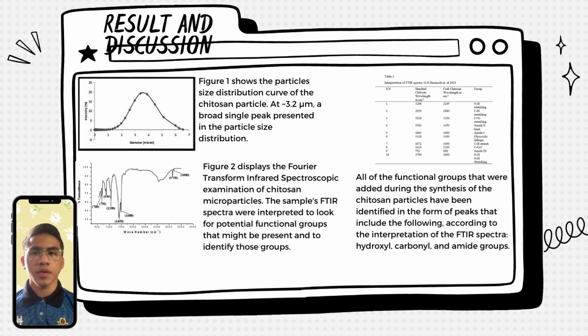The second one, figure 2 displays the FTIR examination of Chitosan microparticles. The FTIR spectra were interpreted to look for and identify all potential main functional groups that might be present in the Chitosan microparticles. In table 2, all the functional groups present during the synthesis of the Chitosan particle have been identified by peaks from the interpretation of the FTIR spectra: hydroxyl group, carbonyl group, and amide group are present.